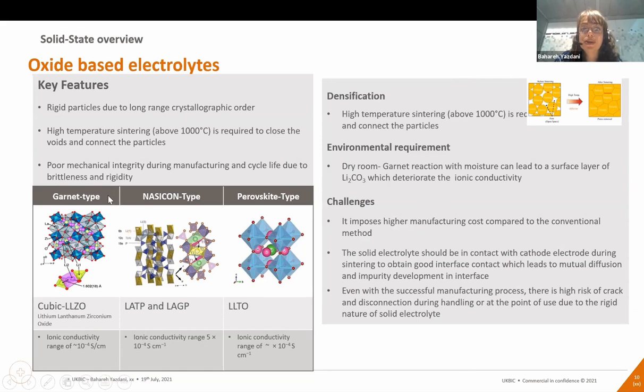So as I mentioned, oxide-based electrolytes have very rigid particles, and this is because everything goes back to the crystallographic structure of the material. Their crystal structure is very ordered. That's why they are rigid, and they need high temperature sintering, as I mentioned, for densification. This rigidness and brittleness make them a little bit difficult for manufacturing, and also it needs to be guaranteed that after manufacturing, during use, there is still good contact between interlayers for the performance.